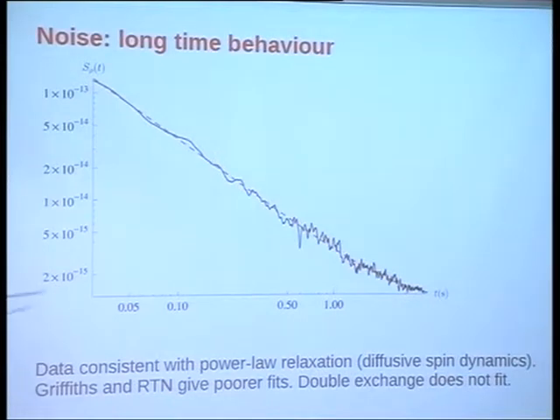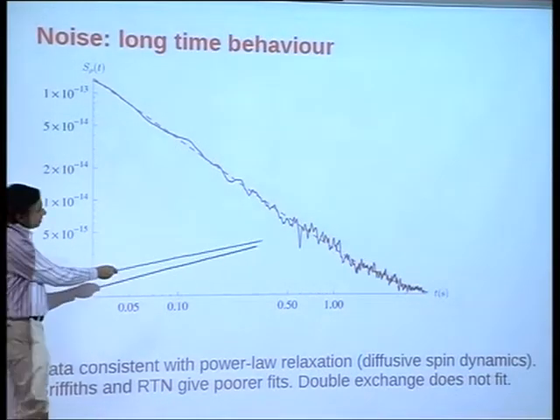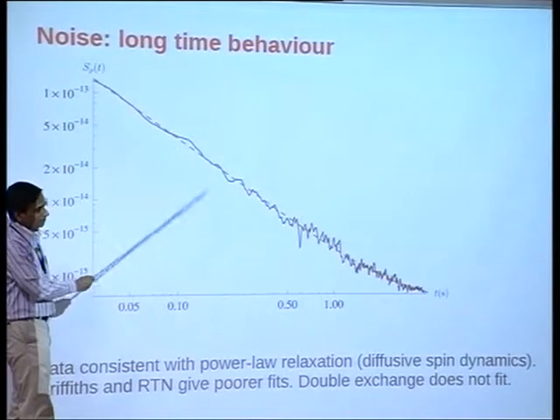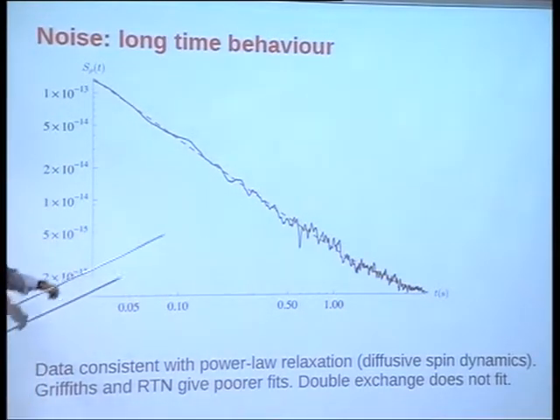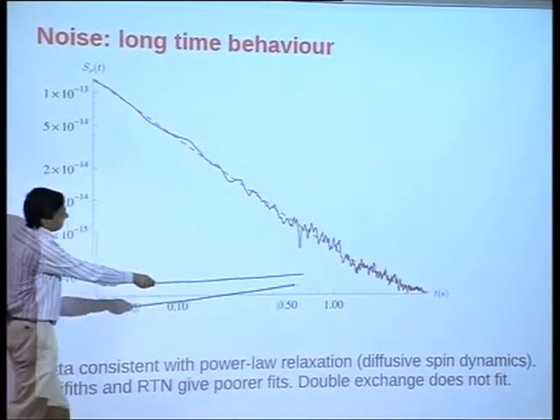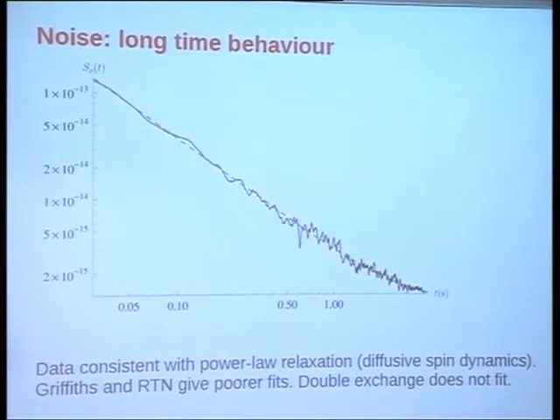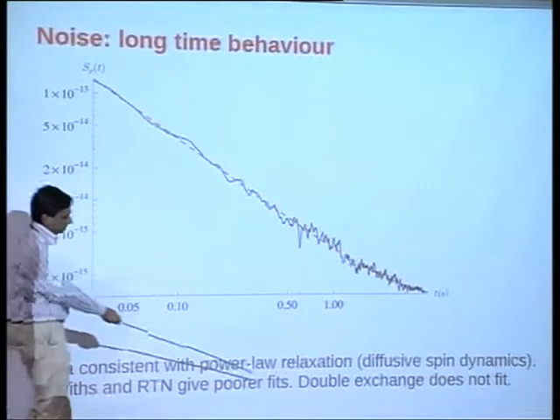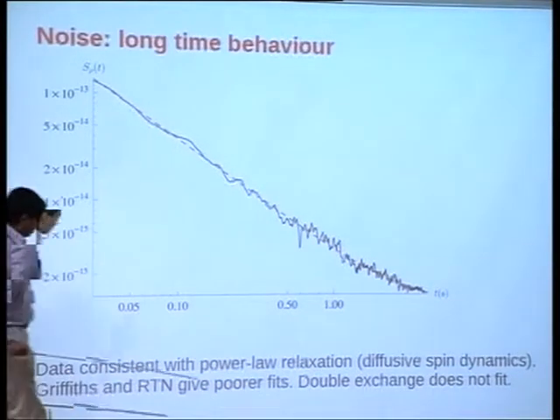In this case, I've just shown the matching with model B dynamics. This is a fit to 1 over t plus some small logarithmic term which comes from the 1 over f background. But it's very well described by model B dynamics over a wide range of noise. Likewise, we have tried to fit it with Griffiths and random telegraph. They give much poorer fits. Double exchange also I tried. It does not fit.